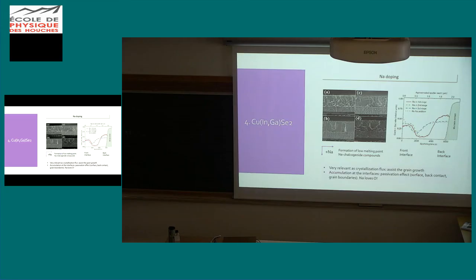Really, this is kind of universal. You need sodium, it doesn't matter how to introduce it. You can see some of the effects of sodium, larger grains because it creates some flux for crystallization, and one of the characteristics is that sodium tends to accumulate at the interfaces. This is one of the reasons: sodium likes oxygen, so where oxygen is, sodium will diffuse naturally.